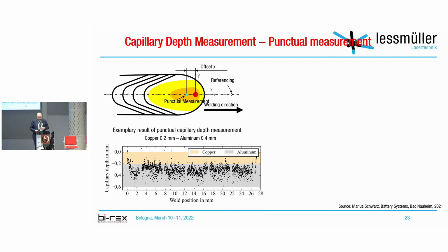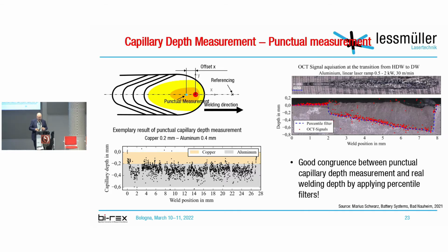This is a real sample where copper is welded onto aluminum, and you can see where we have measured, slightly behind the TCP. All the black dots are the measurement points, and the art now is to find the right algorithms to really measure the lowest point. The problem is the keyhole is highly reflective. The keyhole is nothing stable. It's always moving around and changes its shape all the time. So we have to find the algorithms and identify the values that really represent the lowest point.